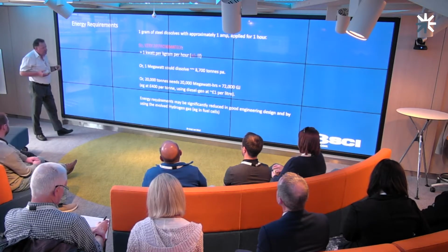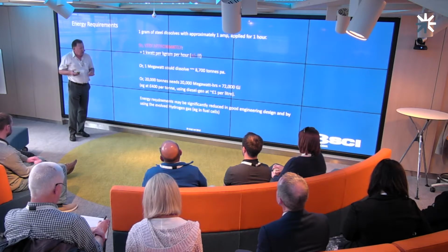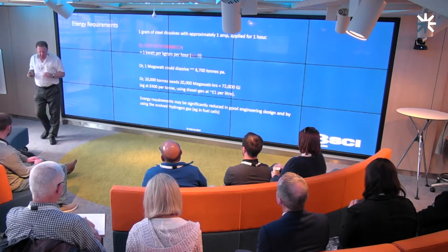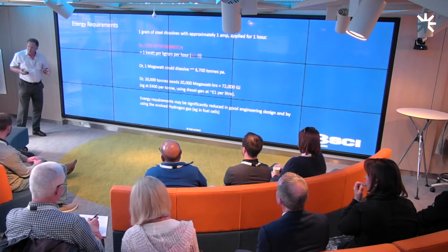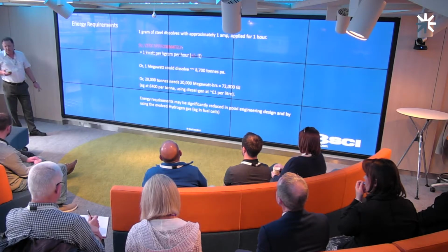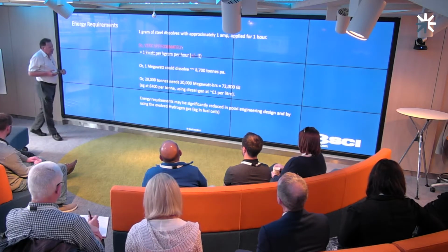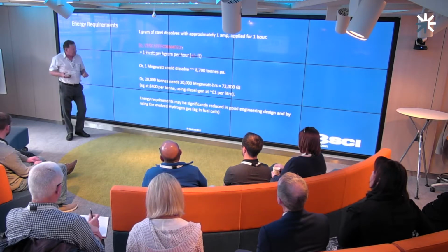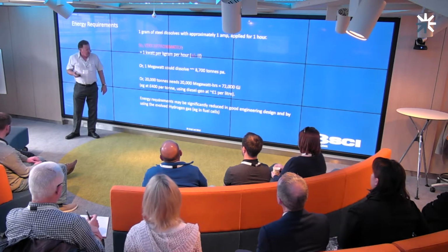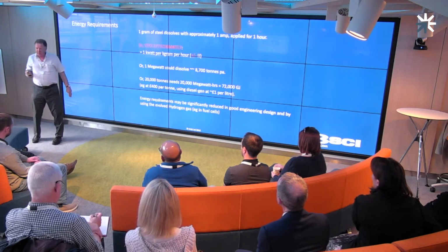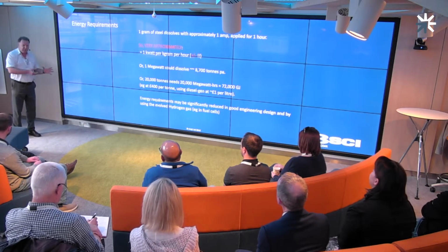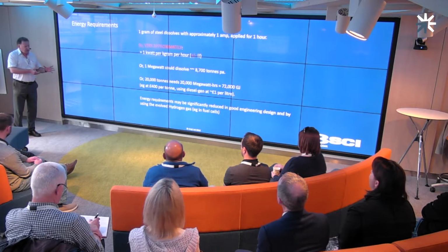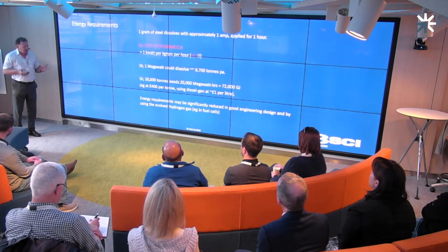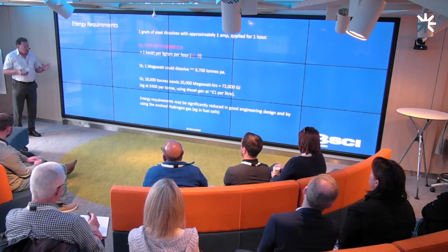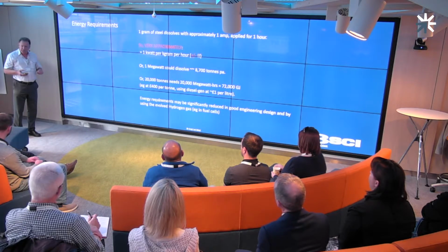So just by simple extrapolation, you can see that a kilowatt of power, going with the view that we are reasonably confident we can keep the resistance of the circuit at significantly less than 1 ohm, will give you about 1 kilogram an hour. And if we linearly extrapolate that, thinking very ambitiously as to what we may eventually be able to achieve with this technology, quite simply, a megawatt would dissolve 8,700 tons per annum. So you can see immediately that from this very simple piece of electrochemistry, I don't think these are unrealistic expectations that we get through linear extrapolation. We could actually be dissolving quite significant quantities of steel by using relatively high powers.